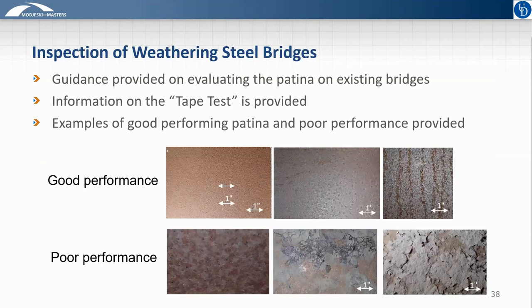Next slide. So moving out of construction, once the bridge is constructed, the manual provides guidance on appropriate ways to inspect weathering steel bridges, and guidance on what the appropriate surfaces should look like. There's some photos there showing good performing surfaces, and further down below, some poor performing surfaces, what to look for as an indication that your patina is not adequately forming. There's something called a tape test that's detailed in there, where you take some packaging tape and apply it to the surface and pull it off, and then the amount, shape and size of any rust particles that come off will tell you whether the patina is performing correctly or not.